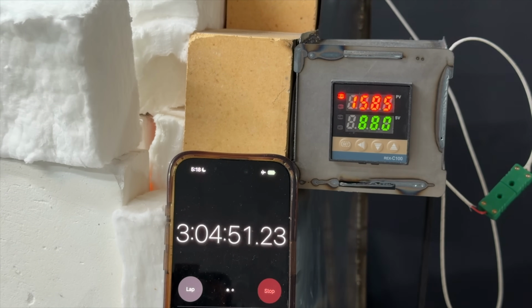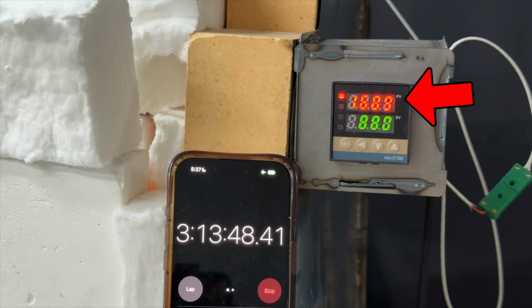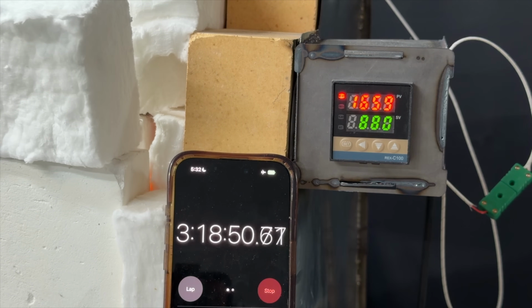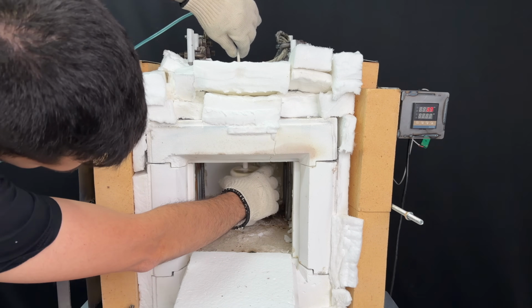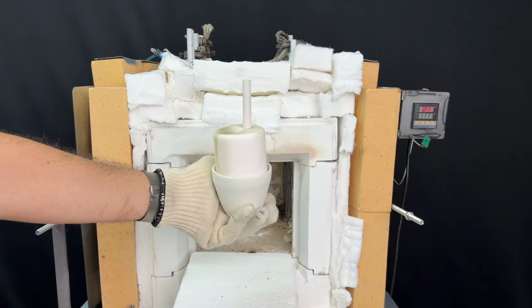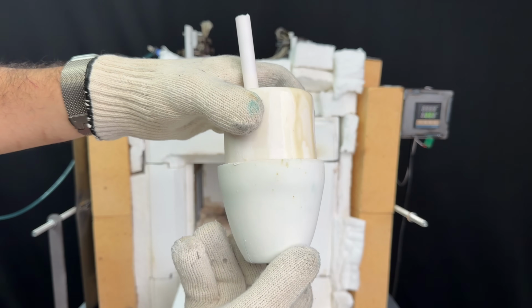This indeed worked and got us up to 1660 degrees Celsius, just 8 degrees shy from the titanium melting point. This is a very productive moment for me. In fact, we got so hot that we seemingly sintered the alumina crucible together. Look at how deformed that is.